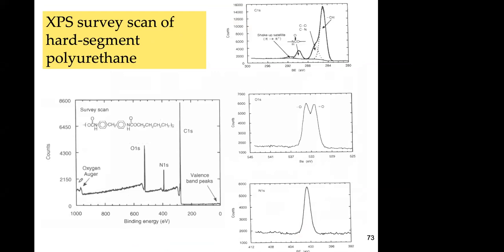Here is a spectrum of a polymer. And here you have carbon, nitrogen and oxygen. You have an Auger line for oxygen, and the valence band spectrum is down here near zero. So if you look closer at the carbon 1s, you can see the different functionalities. These are the hydrocarbon, the carbon with oxygen and nitrogen. And here you have carbon with nitrogen and oxygen. And here you have a satellite peak. That's a shake-up due to a pi-pi* transition.